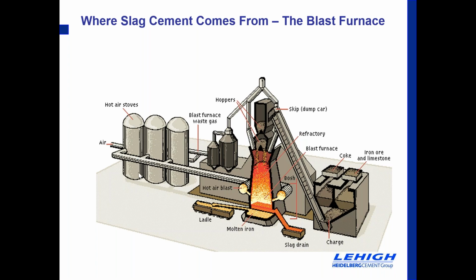So the main difference is that the finished product, the slag, which is floating above the Fe, can be characterized more as a dicalcium system. What we're really missing is the C3A and C3S that we find in Portland cement, but everything else is there. Another way to look at it is typically calcium in Portland cement runs 60 to 65. Calcium in slag tends to run between 38 and 42%, and most fly ash is below 10. So the fact that slag cement can be viewed as a hydraulic cement shouldn't come too much as a surprise when we look at the genesis, where it's coming from, with that vertical cement kiln versus the horizontal cement kiln. So let's look at what happens to the slag floating on top of the Fe.